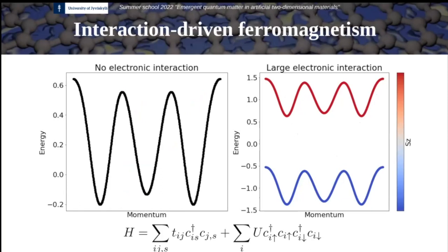And now here, let me show you a very specific example, which is with the electronic structure of vanadium diselenide or vanadium disulfide, which can be described by a single orbital model in the triangular lattice. So vanadium disulfide and diselenide, they also have a charge density wave that it is not included here. But if they didn't have a charge density wave, their band structure would be this one. And according to the quantum chemistry calculations, they actually have a ferromagnetic instability that gives rise to this type of electronic structure.